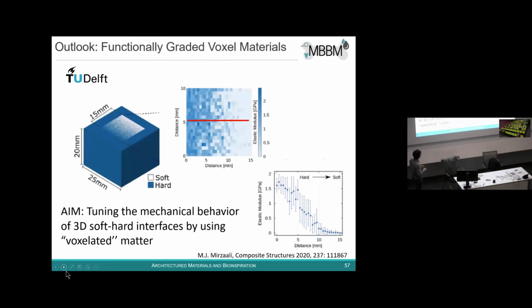and replicate in the attachment of dissimilar engineering materials. So in this example here, we are trying to engineer the interface between a hard material and a soft material, which will be here. The frame around is just printed because we need to cut with the cryomicrotome. But now let's only consider this direction, going from a very hard material to a very soft material. And we do this by depositing hard or soft voxels. By changing the spatial arrangement of those voxels, we are trying to understand how the elastic properties change across the interface and how we can program different spatial configurations of soft to hard voxels such that the interface shows increased failure resistance.